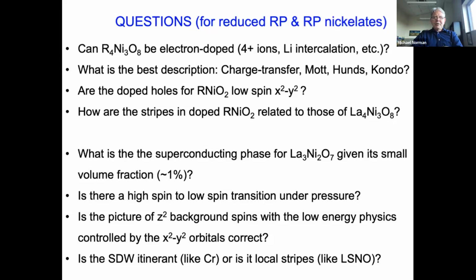A picture we've come up with is that the z-squared spins, the 3z² minus r², are basically background spins, where the x² minus y² can either polarize along or anti-parallel to the z² spins. But the basic physics seems to be that the low energy physics might be controlled by the x² minus y² orbitals. But a lot of people think that z² plays a fundamental role. And is this density wave state itinerant like chromium, or is it sort of like local stripes like we expect for the LSNO compound, the 2,1,4 nickelates? And so with that, I will end.